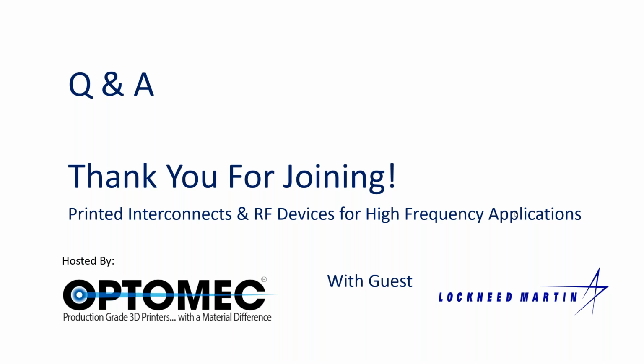Sure. Thank you, it's a very good question. As I mentioned, we're printing nanoparticle inks, so the resistivity of the material after the sintering process is higher than a bulk wire. So the cross section definitely matters, and the uniformity of that cross section will impact the current carrying capability. The wires that are printed can exhibit some ohmic sintering at higher resistance measurements, and we get around that by taking the package itself up to a high enough temperature to get the full sintering of the ink.